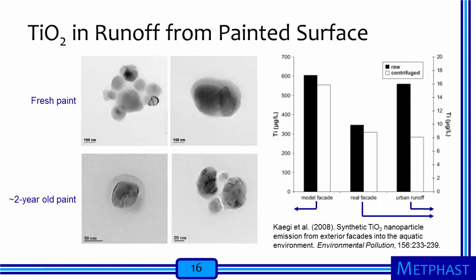The concentration of titanium in the runoff from the surface painted 2 years previously was much lower, on the order of 10 micrograms per liter. Again, most of the mass was associated with particles smaller than 300 nanometers in diameter. The concentration of titanium in the urban runoff measured about 16 micrograms per liter, although only about 50% of this mass was associated with particles smaller than 300 nanometers, likely because much of the titanium came from sources other than facades coated with paints containing titanium dioxide nanoparticles.